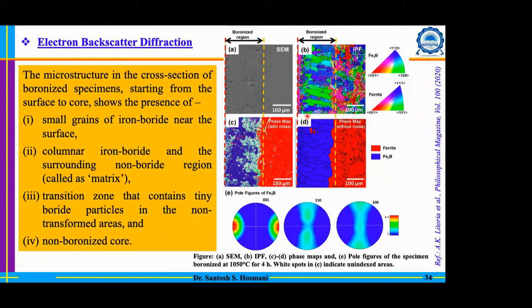And why are those fine grains forming there? Most likely, the matrix which is left between two boride columns is transformed at a later stage into tiny boride, but it is unable to grow because it is already restricted by the well-grown boride columns. So that's why they remain as very fine grains there.